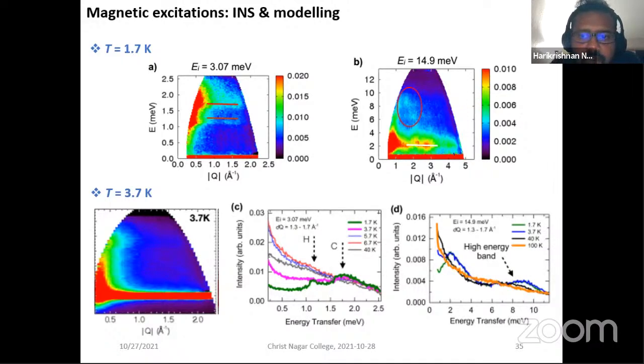And then at 14.9 meV, you would have very weak intensity coming even up to 8 meV. The two red bands on panel A actually merge into one. Here you can see there is a white line, and that's how it is merged into one. So those are the energy bands of the excitation that we are talking about.